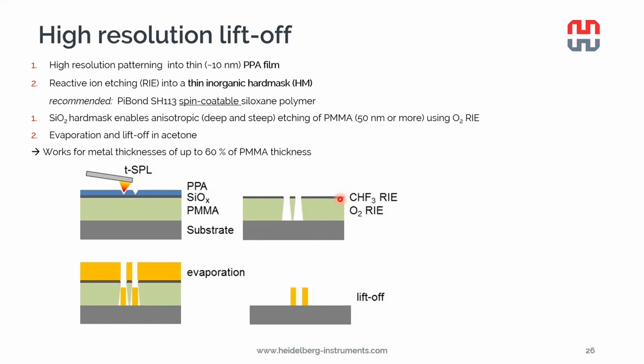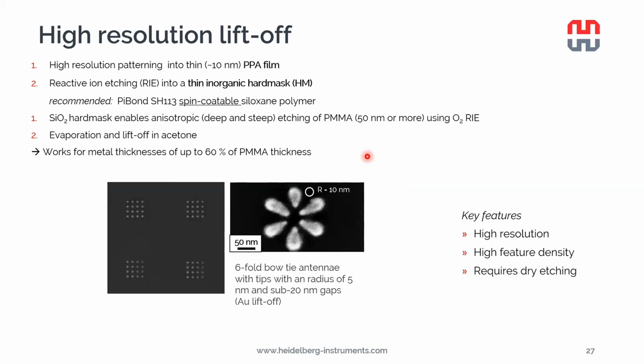In this case, the undercut that develops is much smaller than in the case of the bilayer liftoff. And we can actually evaporate up to 60% of the PMMA thickness in metal, and then carry out a liftoff by dissolving the PMMA in acetone. Here's an example structure, just a 6-fold bow tie antenna, where the tips have a radius of about 5 nanometers, and the gap between each of the leaves is less than 10 nanometers. This was a lift-off in gold.